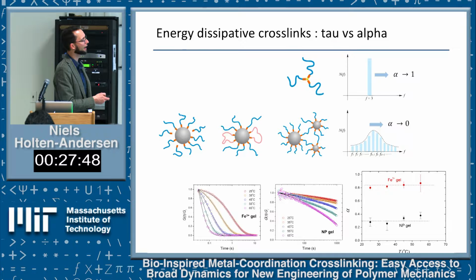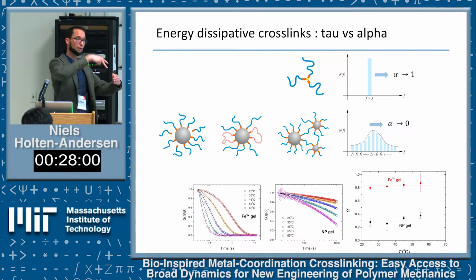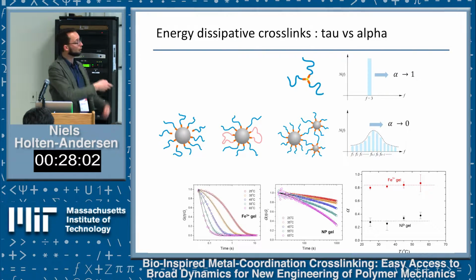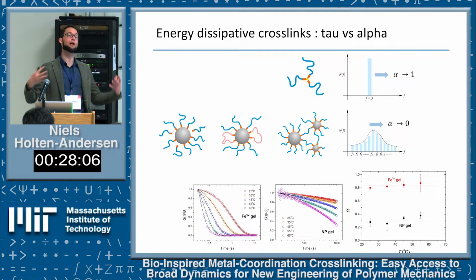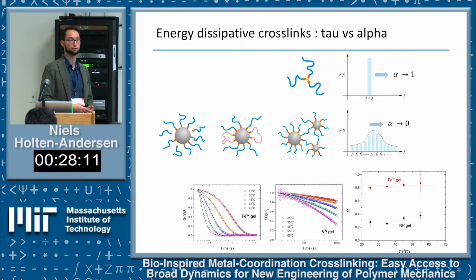We can play with the size distribution of nanoparticles, and with how efficiently the polymers actually bind the particles. Because you have many polymers bound per particle, for this whole structure to relax stress, you need all these polymer ligands to actually pop off the particle. That spreads out the energy dissipation over time, and that's ultimately a good way to engineer toughness—a very simple way, using dynamic crosslinks.